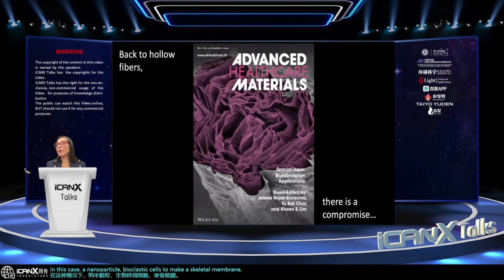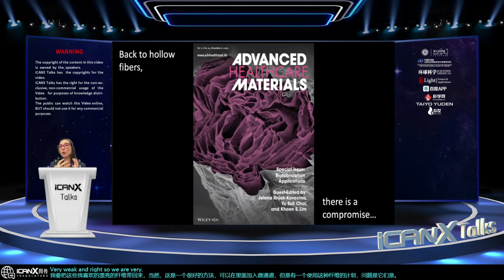And well, I'm going to bring back this beautiful fiber that I love. And of course, this is a very nice way to incorporate microchannels inside, but there was a problem with this fiber. And the problem is that they are very weak, right? So we are very effective in incorporating hollow channels or microchannels inside, but the compromise is that they are very weak. Actually, we could sustain with these particular fibers only 7 days of culture.